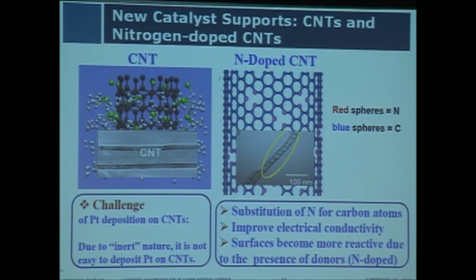Initially, when he talked with us about carbon nanotube functionalized carbon, we immediately pointed out we don't want that type of functionalization because oxygen is something we don't want. So nitrogen doping or any other type of doping might be something we want to try. For that reason, we chose nitrogen doping as a new functionalization method for the carbon nanotube. Very fortunately, normally we worry that with any doping on this carbon nanotube, the electric conductivity will be an issue. Very fortunately, we got improved electric conductivity and at the same time improved platinum dispersion.